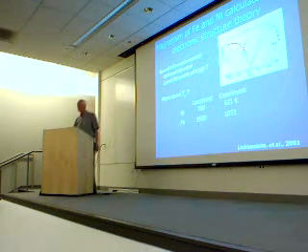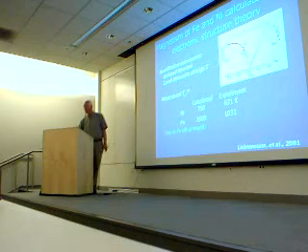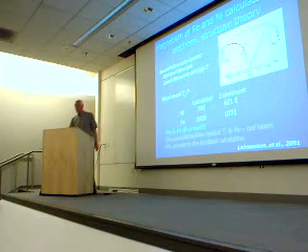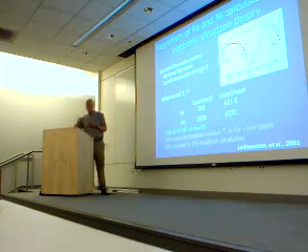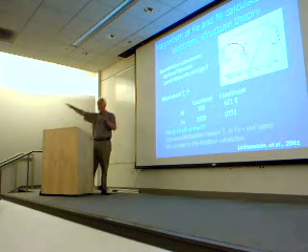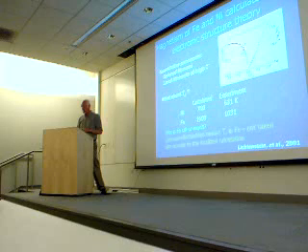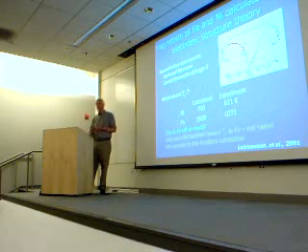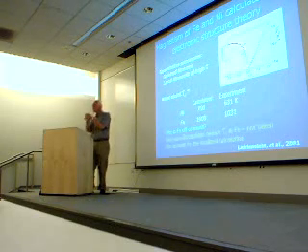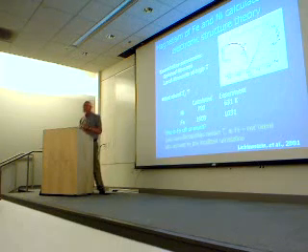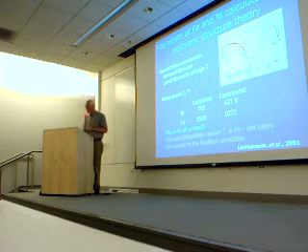Have any idea why nickel and iron might be different? I didn't. I get this from the experts in the field. It's basically that there's something that's not being taken into account well in iron that is much better in nickel. In iron, there are these long wavelength spin waves that contribute a lot to the fluctuations that decrease the Curie temperature, and not so much in nickel. And these local pictures, where you're dealing with one atom and its surrounding neighbors, just don't take into account this long-range stuff. So you see that people starting from high temperatures have a way to go too.